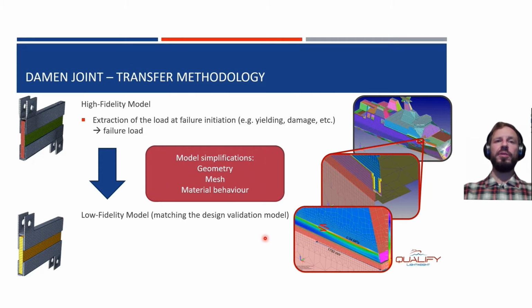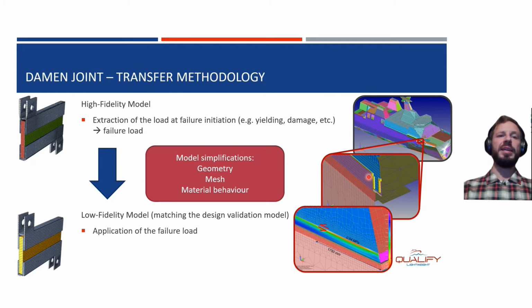That's not of interest, because at the point where the failure initiates, none of these effects has taken place yet, so we can discard them, such as has been done in the design validation model, such that the low fidelity model now matches the design validation model in terms of mesh, geometry, and material behavior. Then as a next step, we take the failure load that we extracted from the high fidelity model and we apply it to the low fidelity model.